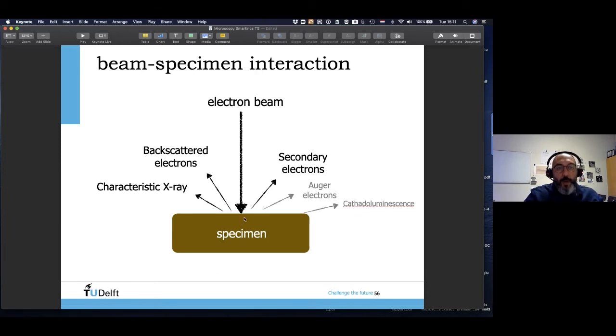And when this happens, of course, some collisions happen, and as a result, you will get secondary electrons like this. You remember they were mainly coming from the surface because they are low in energy. Although we are generating them in the bulk, they will not have enough energy to escape and go to your detector. So that's the reason we're mainly getting information from the secondary electrons from the surface. Backscatter electrons, again, are energetic enough. That's the reason they're coming from the surface as well as from the bulk.